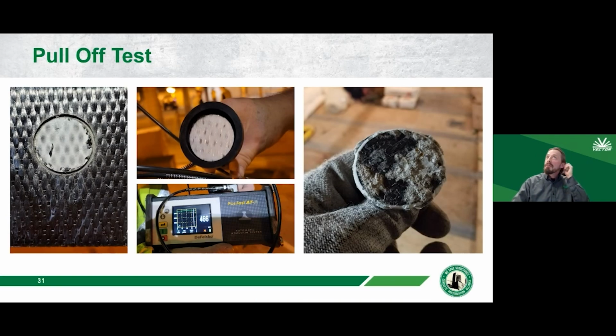So a pull-off test is pretty straightforward. These can be done at random, and then you would have to put another piece of carbon fiber over the top of it. Or a lot of times what we'll do is we'll put an extra piece up that we can use for testing so that we're not putting holes into the fabric that is part of the design. This will tell us if we've mixed our epoxy correctly, that we've got the correct surface prep done on the concrete itself, and that the installers have laid and installed the fabric as tightly to the concrete as possible.